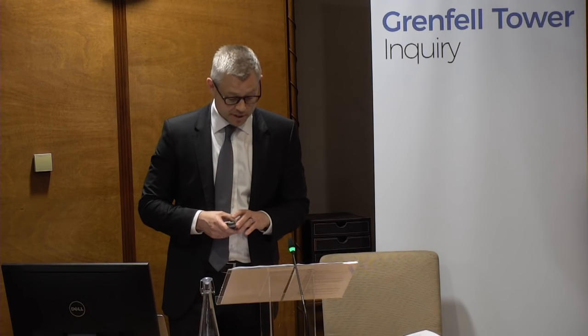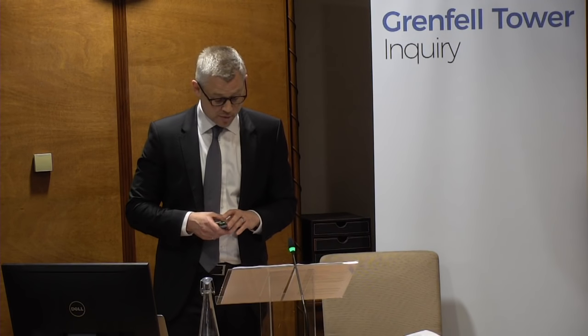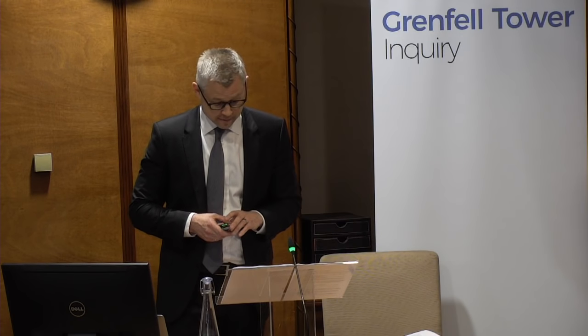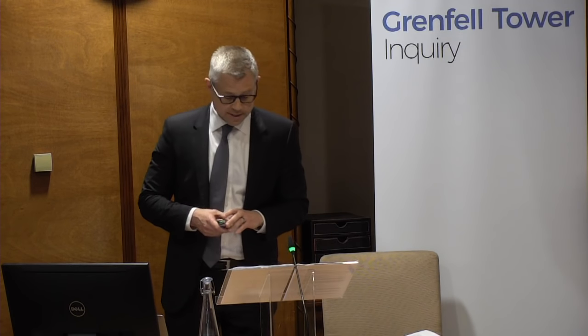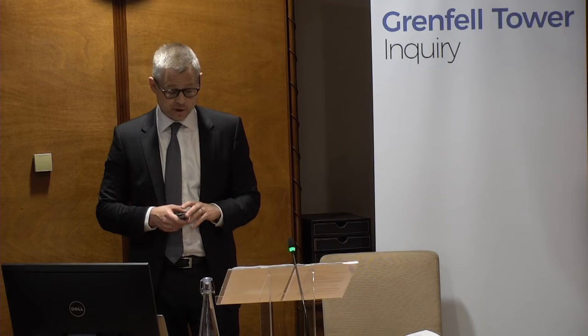However, as I've just mentioned, downward flame spread may also be significantly influenced by melting and dripping of burning material, as I showed a few moments ago with reference to polyethylene. In all cases of upward, downward, and horizontal flame spread, the spread is dominated by the heat release rate of the existing fire, how the resulting fire transfers heat to the unburnt material, and the thermal properties of the material itself.